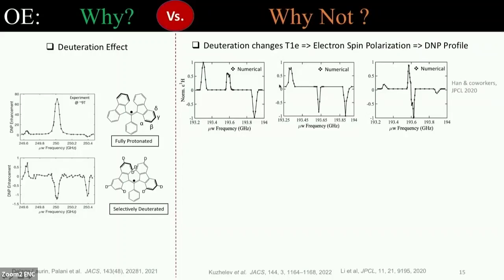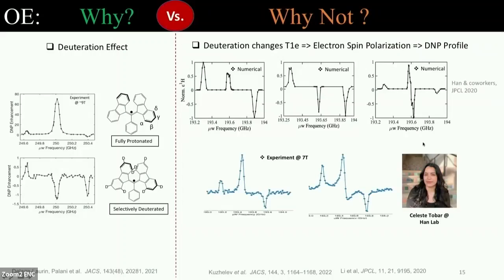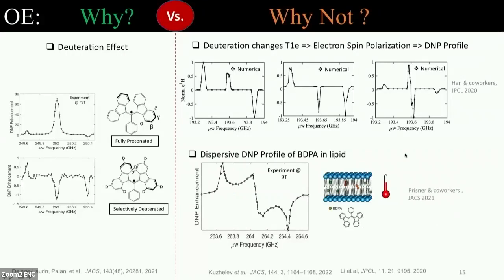This is something that we first numerically showed the year before last, that the DNP profile for a clustered system could be positive, it could be negative, or it could be dispersive. And very recently, a PhD student in Songi Han's lab showed experimentally that indeed, for the same radical system, BDPA, it's possible to switch the DNP profile from, say, absorptive to dispersive. And also, very recently, Prisner and co-workers have shown BDPA, when dispersed in lipid, gives rise to a thermal mixing profile. So it's a dispersive DNP profile in the center.